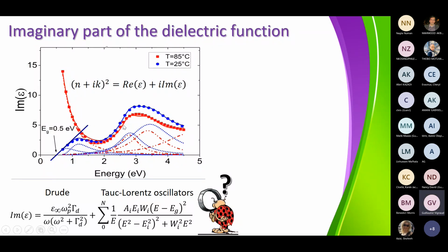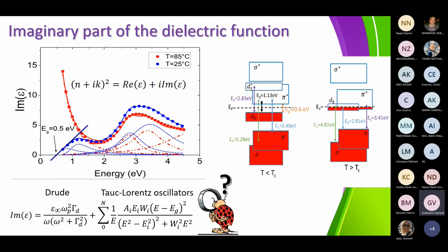And so if you look at how we deal with this, in the red one, you can see that here there is one bump, another one here. And well, that's the red one. For the blue one, there is one here, one here, one here, one here to describe totally the dielectric function. So you fit that with those Tauc-Lorentz oscillators, you get specific values. And from those specific values, then you can say, oh, how is the band structure of the material? And you see here that